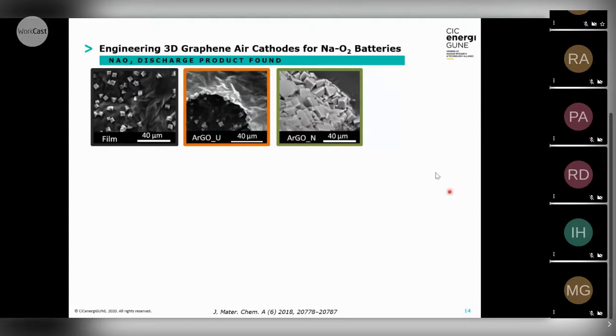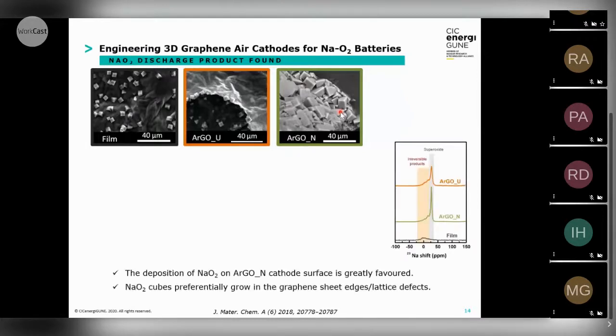So we wanted to understand what the difference of these materials is, and we looked at the discharge product, and we found that the discharge products were really the same, sodium superoxide, which has this cubic morphology. But in the case of the film, we have only small cubes in some parts of the surface. Then when we go to this sample, we can find some of the cubes that grow on the edges of the graphene sheets and some on the surface. And then for the sample which outperforms the others, we see the entire surface covered by this sodium superoxide, meaning that we have utilized all the surface area.